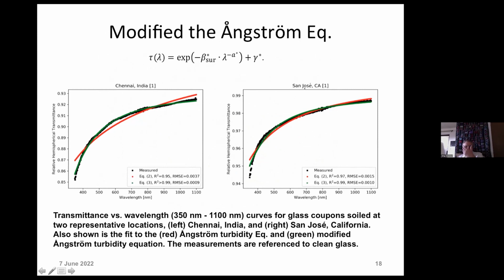We also fit in the paper, you can see Egypt, we looked at Colorado, we looked at Spain, we looked at other places. In each case, we found that the R squared was very high, and the error, the root mean square, RMSE, very low, if we used the full form of the equation, which contained this gamma offset. You can see that when you do include it, it models the data quite well.